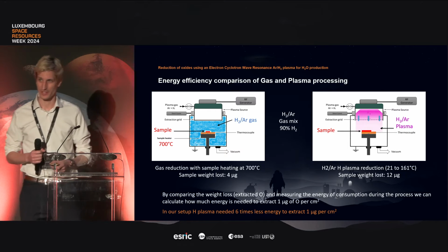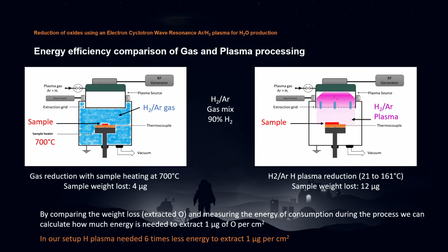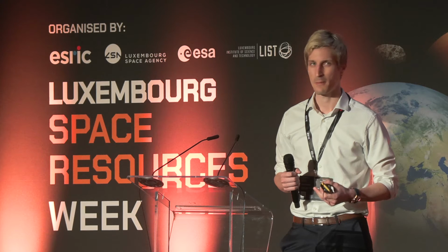First things first, we wanted to compare the efficiency of these two processes preliminarily in our chamber. So we filled the chamber with the hydrogen-argon gas mixture on the left, and we heated the sample at 700 degrees, and we collected the weight loss of the sample after that. We repeated the same process, but in this case we did not use any heating. We only utilized the same gas pressure with plasma, and then we compared the processes.